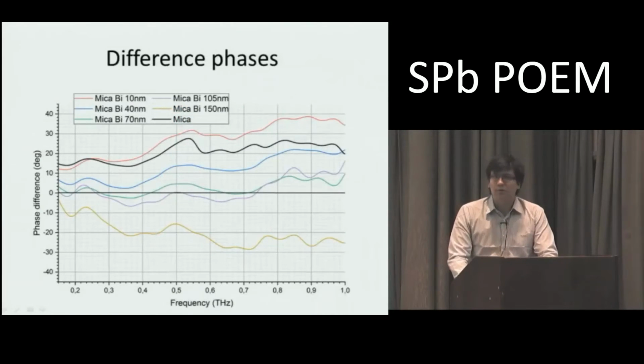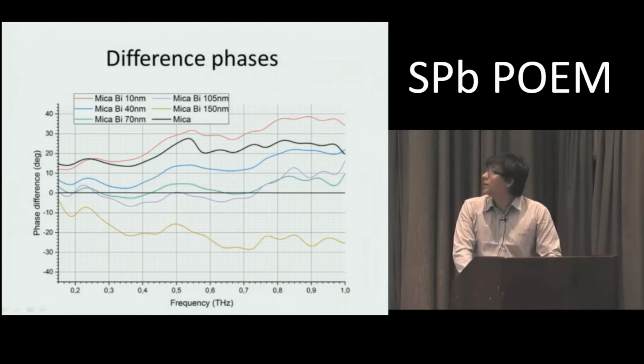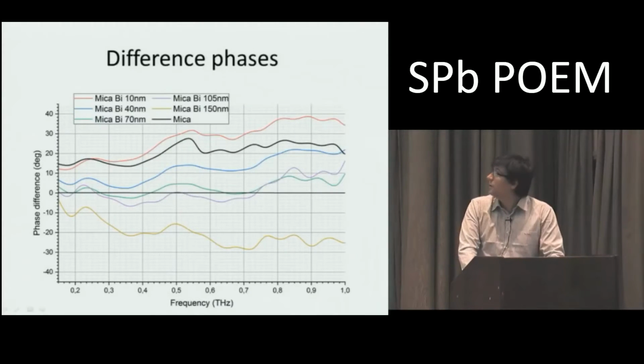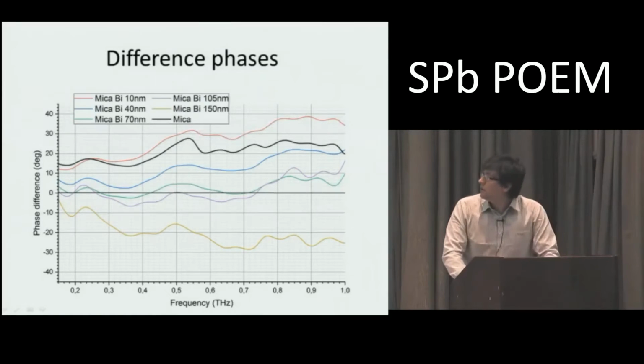And after fast Fourier transform, we show the phase spectra, and we can show that a very low thickness of bismuth increases the phase relative to the air phase, and with increasing bismuth layers we have a lower phase difference and then a negative phase difference.